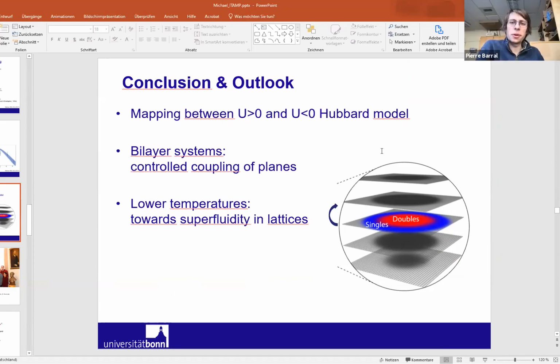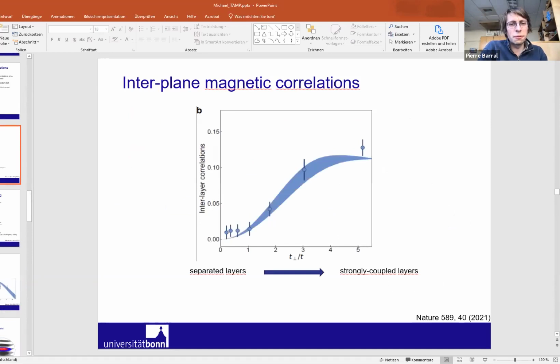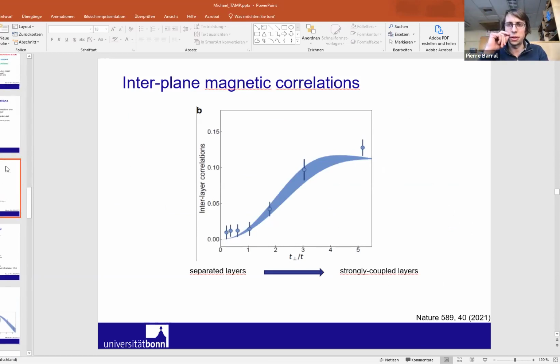I have a quick question for the correlation in the transverse plane, like in the bilayer thing, because it seemed to saturate on the plot when you had correlation as a function of t. It starts up and then saturates to something that looked like a lower value than what you had for the antiferromagnetic ordering. So I understand the rising up of the correlation, but why does it flatten out, and should it flatten out to some higher value, or what should we expect here?